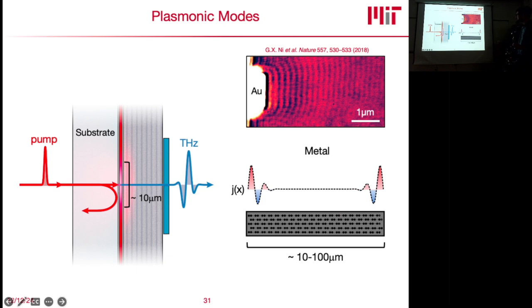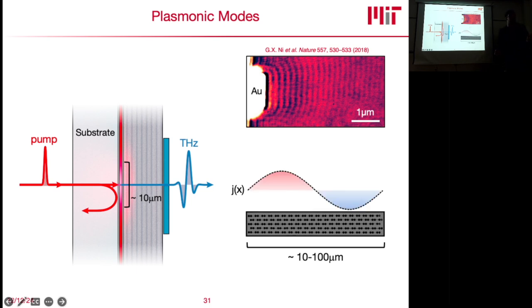However, in the middle, it would still probably behave like a normal metal because the scattering is too large. We will not see the boundaries. So what we want to actually look at is a long wavelength plasmonic excitation in these materials, as I've shown before, where you have currents going one way in one half of the sample and the other way in the other half, which evolve on the order of 10 to 100 micrometers. This is something that we can actually measure with